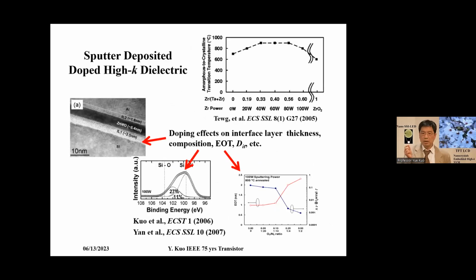The third example is sputtering deposition of high-K dielectric. For high-K dielectric, conventionally people use CVD or ALD. CVD and ALD deposit metal oxide for high K. There is a common problem. For example, hafnium oxide has a low crystallization point, 600 degrees C. For device fabrication, the temperature is usually higher. The crystallization of the gate dielectric will cause reliability problems.